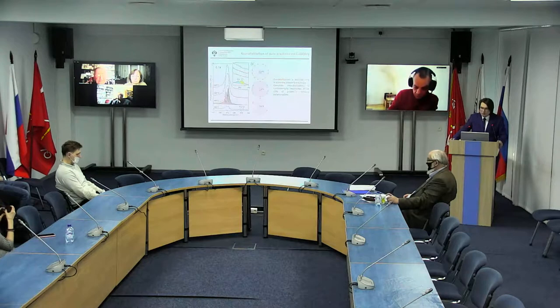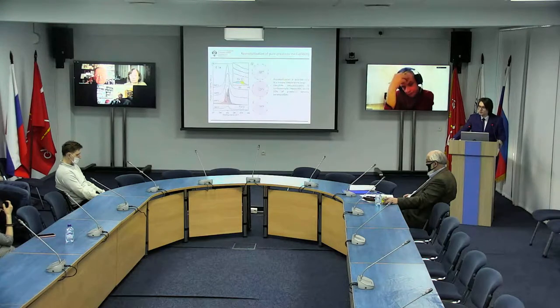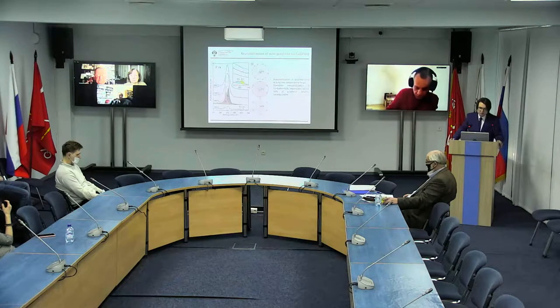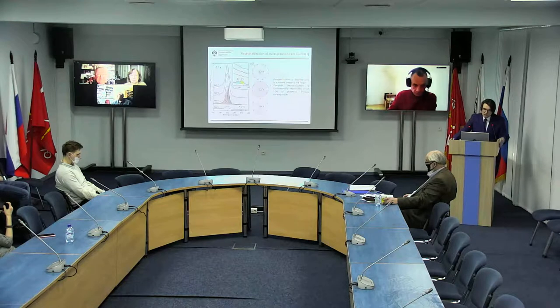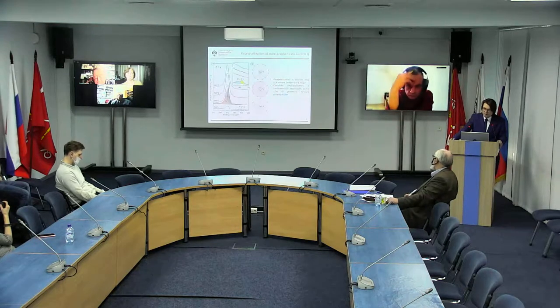Recrystallization of pure graphene on cobalt. Let's start with pure graphene. On this slide, we see the evolution of the C1s spectrum of graphene and the appropriate images depending on the temperature of heating of graphene. And we see that initially polycrystalline graphene during heating at temperature 750 degrees is becoming monocrystalline, and we see it by the characteristic split of the C1s peak and nearly full absence of curve-like reflexes.